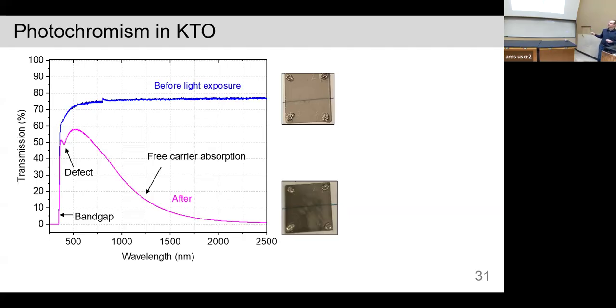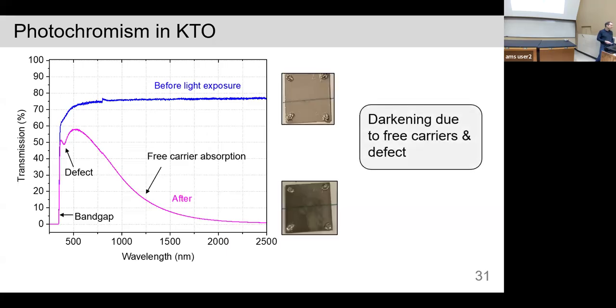And here's just a couple of pictures. It definitely has this kind of dark grayish color. And so this defect is very, very interesting. And it's definitely something that we are continuing to study. So the darkening is due to the combined effects of free carrier absorption, which goes into the visible somewhat, and then this mysterious defect peak. If it weren't for hydrogen, you might be able to get that defect peak at low temperature. But hydrogen really allows you to do these things at room temperature. Makes everything very, very persistent.